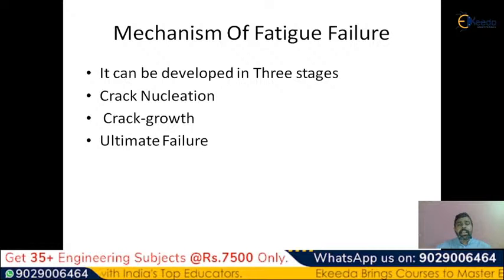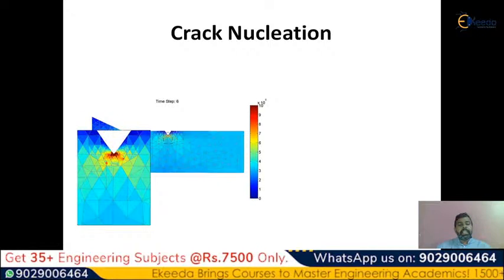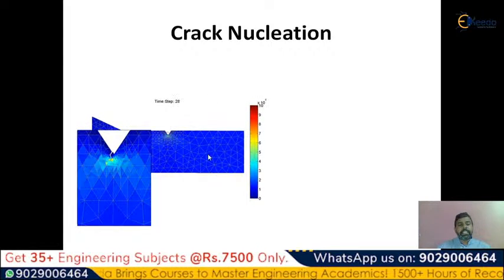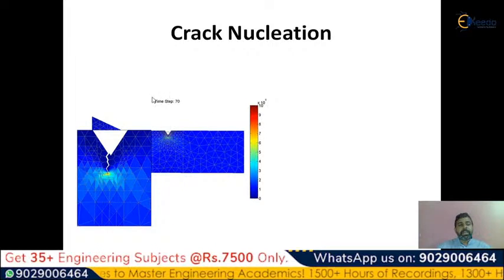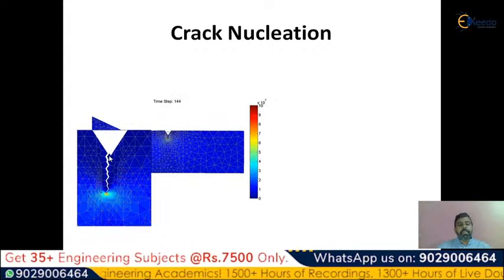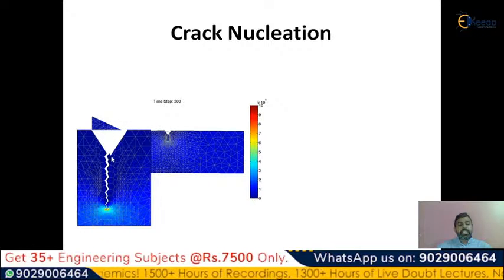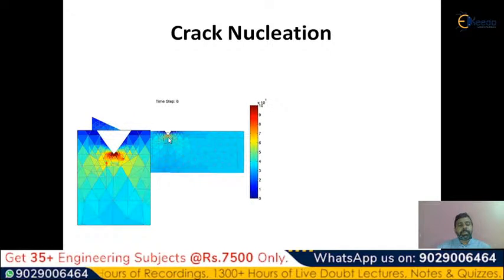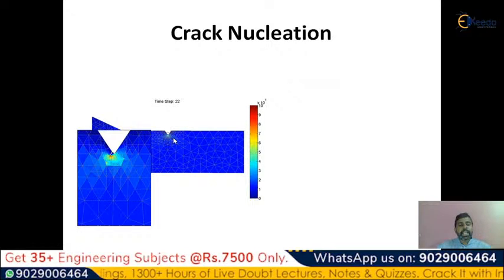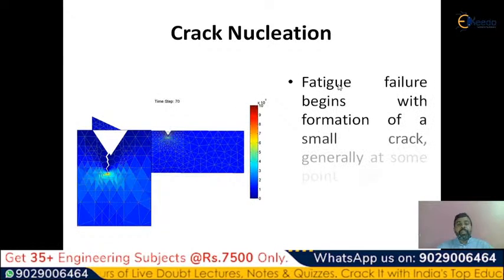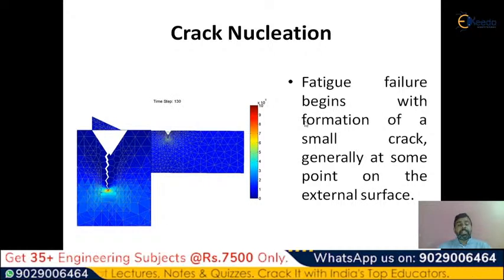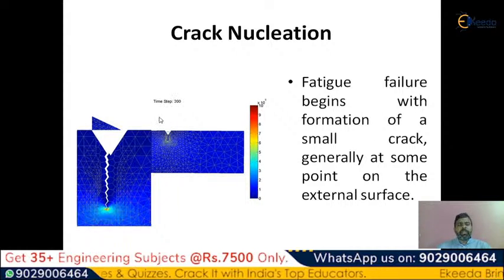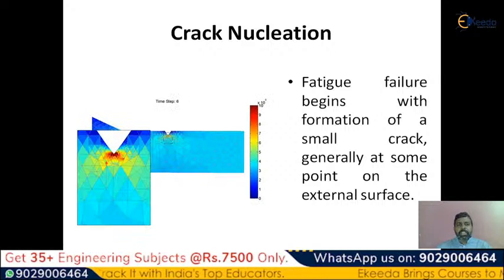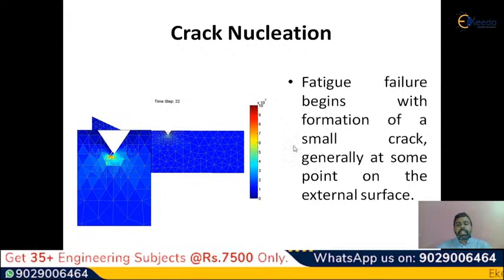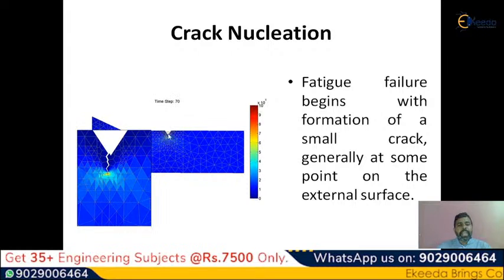The first one is crack nucleation. Crack nucleation means the crack is going to start. See the material here, the analysis which I have done on a particular material using ANSYS software, a crack analysis. You can observe this is the position at which the crack nucleation starts. The fatigue failure begins with the formation of a small crack only. It will not start with a bigger crack. It will start with a small crack, generally at some point on the external surface.